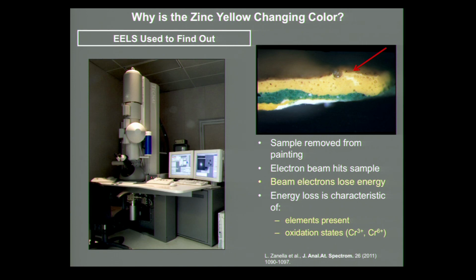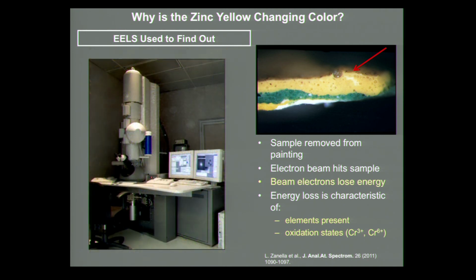So in terms of understanding why the zinc yellow is changing color, a technique called EELS was used in order to find out. And you might think, okay, I'm feeling good, I know what an eel is, but in fact, this is not the eel we're going to talk about. We're going to talk about electron energy loss spectroscopy. And the way that this technique works is that you remove a tiny sample from the painting and hit it with a high energy electron beam. And the electron beam loses a very small amount of energy when that happens.